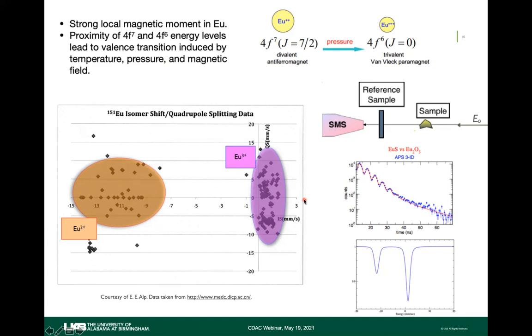Yeah, I think we know at least for the case of europium oxide, when we compare Mossbauer and XAS, there seemed to be some sort of parasitic isomer shift increase in the Mossbauer under pressure, and because of course the valence is also changing, it's complicated. So it will be really interesting to look at, say, europium-3 under pressure with a reference sample, and see whether the effective valence increase is really a parasitic change and not a real valence change.